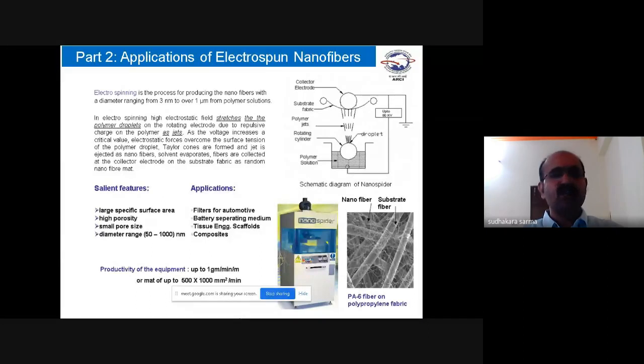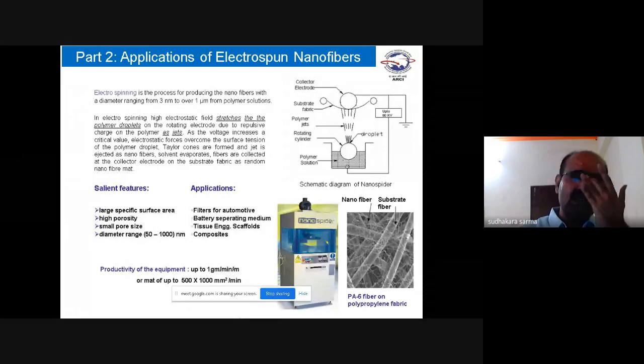Yeah, applications of electrospun nanofibers. Electrospun nanofibers. I am working at the Center for Nanomaterials and dealing with nanomaterials. We have set up an electrospinning facility at ARCI. With that, we are producing nanofibers from polymers with a fiber size of 3 nanometers to 1 micron, that is 1,000 nanometers. The principle of electrospinning is here. As I said, electrospun nanofibers are made from polymer solutions. We load the polymer solution into the tray. You can see the schematic diagram of a nano spider.